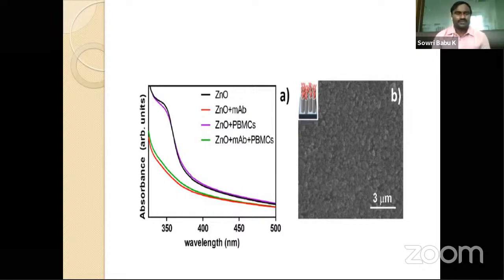But when we attach monoclonal antibodies to the zinc oxide, we lost the absorption peak. That itself indicates monoclonal antibodies have successfully attached to the zinc oxide nanorods. Again, we also measured zinc oxide plus monoclonal antibodies plus PBMCs. Then also we have not seen an absorption peak of zinc oxide. That itself confirms the direct immobilization of these antibodies, NKP30, on the zinc oxide nanorod surface.